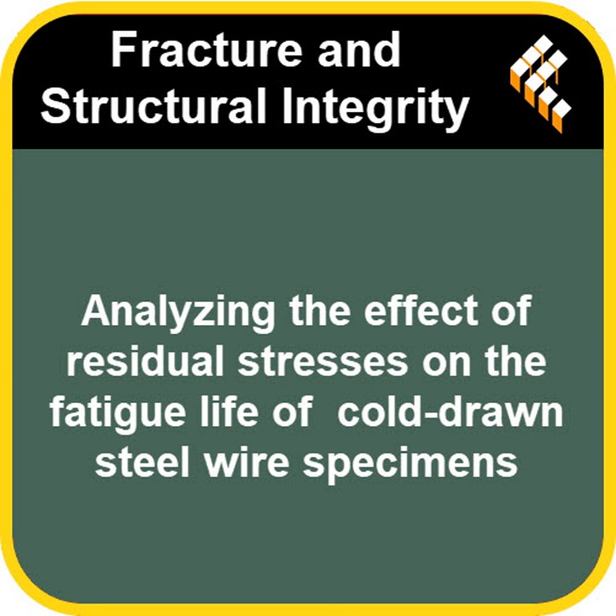That was one thought. But the second theory, which they felt was more reasonable from a mechanical engineering standpoint, was the stress reduction approach. This suggested that the pre-existing compressive residual stress, mainly near the surface from the cold rolling, this compressive stress acted to counteract the tensile stresses applied during the fatigue test.